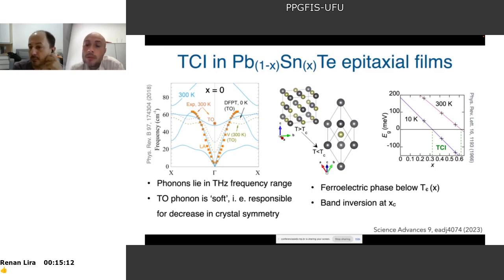But more and most important, the gap decreases when you increase tin concentration, here X, right? When you increase tin concentration, the gap decreases until it reaches this point when it closes around 0.3, and then the gap opens again but inverts. And in this inverted phase, we have the topological crystalline insulator phase. This point depends on temperature. You can see for room temperature it is much higher, but we will make all our experiments close to this point. So here these crosses are our samples, one in the trivial phase and two in the topological phase.